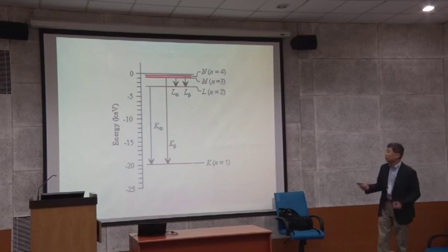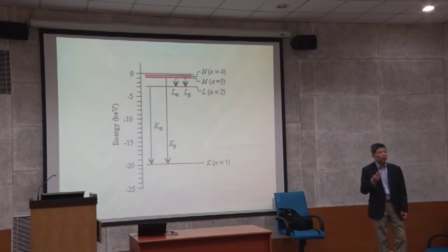So we use specifically the K alpha transition. But K alpha has a splitting of energy too, so we have K alpha 1 and K alpha 2. There are two different wavelengths of the X-ray, and K alpha 1 is about twice as strong as K alpha 2. For some X-ray diffraction, you need very high resolution. You use a monochromator, and then you separate those two lines. They come from the transition of electrons from the next layer, L, coming down here, but this one splits the energy a little bit, and K alpha 1 is the strongest one, coming from the transition from here to here, and that is the wavelength here.